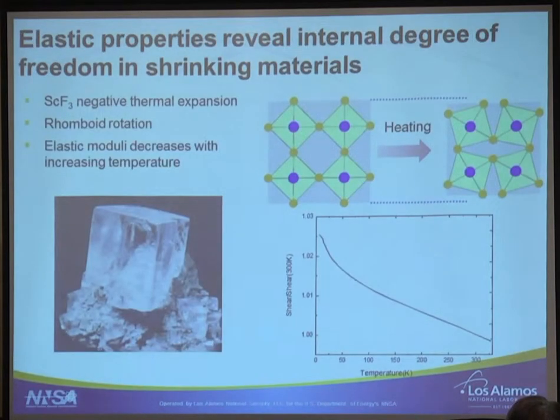So you can get a lot of intrinsic interatomic information by measuring elastic constants. Now, interesting things happen when you measure negative thermal expansion. You would imagine that if the material is shrinking as you get higher temperature, your moduli should increase because you're getting atoms closer. Well, what happens in most materials is different, and I'm showing some examples we measured in scandium fluoride.